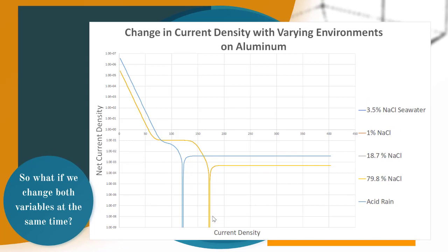Surprisingly, with an increase of salt, there was no change in the current density, which means there would be no change in the corrosion rate because aluminum is passive. However, if the pH changes, then the corrosion rate will most definitely increase. After this discovery, I went further and continued to do simulations to analyze an addition of pH as a variable. What would be a change in the current density because of the local attack from the pH?